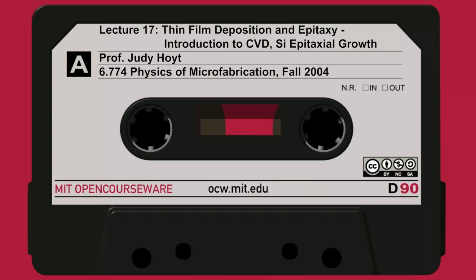So I took the diagram I just showed you, and I chopped off the back end, so what we're talking about is the front end. And there are maybe 3 different types of critical thin films that we're going to emphasize, because this is a course on front end processing. So we're going to emphasize the deposition of silicon, either single crystal by epitaxy or polycrystalline by LPCVD. And here's the polygate. Silicon dioxide, which is also called LPCVD oxide, low pressure chemical vapor deposition, or low temperature oxide, and silicon nitride, which I've shown here in green. The spacers are often made of nitride these days, or combinations of nitride and LTO. So that's what we'll emphasize in this class.